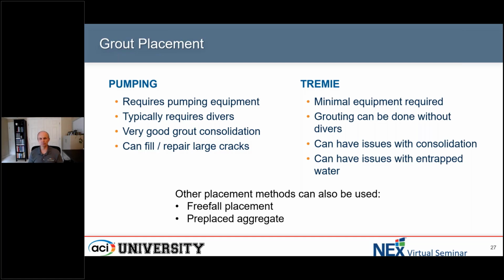And then there are also pre-placed aggregate placement methods where, especially if you're doing very large grout placements, you can pre-fill the forms with a coarse aggregate and then pump grout into that form, forming more of a concrete encapsulation than just a grout encapsulation. And those again are good for very deep placements where you're using a large quantity of material to fill an annular space between the FRP jacket and the existing structure.